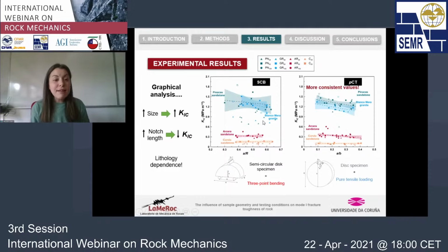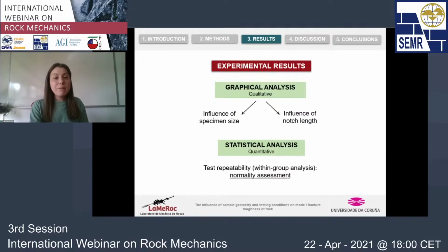But there is something really interesting about this, and it's that we also observed that there was a lithology dependence, that the effect of specimen size and the effect of notch length was not the same for the 4 lithologies that we have used. And it seems, at least apparently from the graphs, that the effect might be higher for the harder materials. But with this graphical analysis, we could only have a qualitative estimation of the